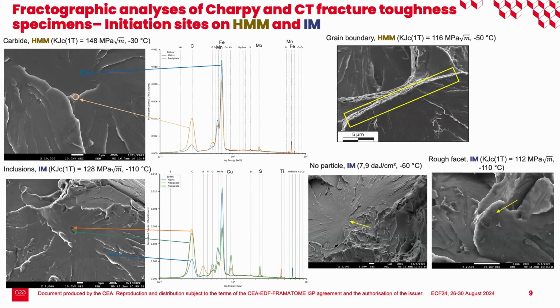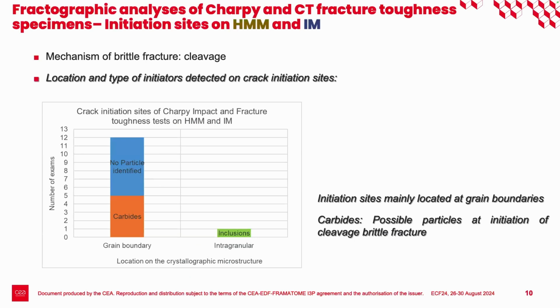Sometimes, like in this example, we couldn't find any specific particles that initiated the cleavage fracture. But in a lot of cases, we could find some very small carbides that have been enriched in manganese and molybdenum. And in only one case, we could find a cleavage initiation from an inclusion inside the grain. If we sum up all these results of fractographic exams, we can say that in the vast majority of cases, cleavage initiates from grain boundaries. And when we find precipitates, these precipitates are carbides. In only one case could we start cleavage from an inclusion. So for the rest of the talk, we will consider that cleavage initiates from carbides.